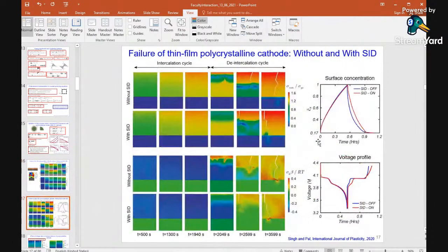And then if we move into the stress distribution, we can see a very complex stress distribution happening when the crack is arriving. During the intercalation cycle, you see that the stress field is pretty much uniform, but during de-intercalation, the stress field is disturbed due to the accumulation of the plastic strain and the development of this crack. Okay, the detailed analysis of why this crack forms we have discussed in the publication. And if we compare the surface concentration, we see there is a difference between the stress assisted diffusion and stress induced diffusion.